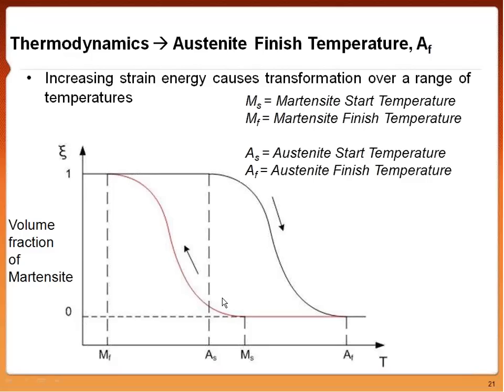So this graph down here is a graph of volume fraction of martensite to temperature. And if we focus first on the cooling curve pictured in red, when we go from austenite to martensite, we see it happens over a range of temperatures, and we have what's called the martensite start temperature, which is where we begin to see pockets of martensite form and the volume fraction of martensite increase. And then we reach a final point where we have complete 100% martensite in the material, which is called the martensite finish temperature.